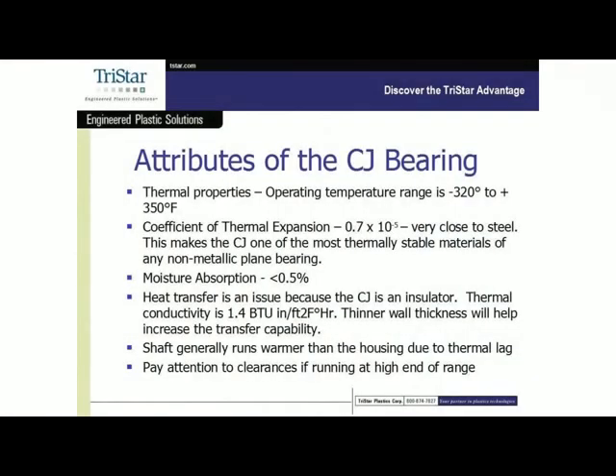Some of the thermal properties, again, operating range is cryogenic to 350. The thermal expansion I mentioned is about the same as steel. Moisture absorption is less than 0.5%. Heat transfer is always an issue with polymers. With the CJ, we've got a thermal conductivity of 1.4. If you have thinner walls, as we showed before, thinner walls have a great effect on the transfer capability of heat.